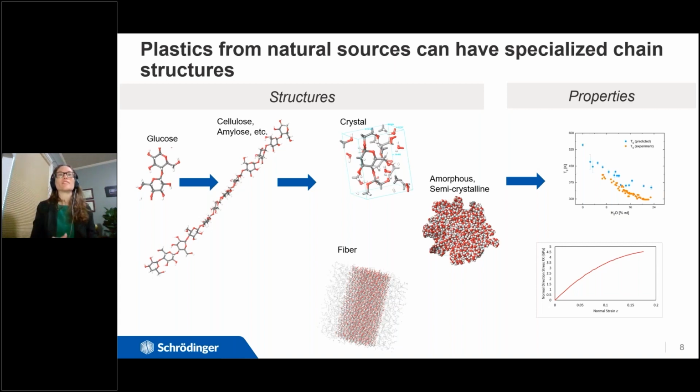So they are, by definition, polymers, but they have really distinct structures as far as the way those units connect together and the way that they form these chains, and the specific geometry within those sugar rings plays an important role in what it is and the way that they perform. So the difference between, say, cellulose and amylose can be very distinct inside the way that the torsions on this particular chain arrange, and you can get different kinds of structures depending on that.